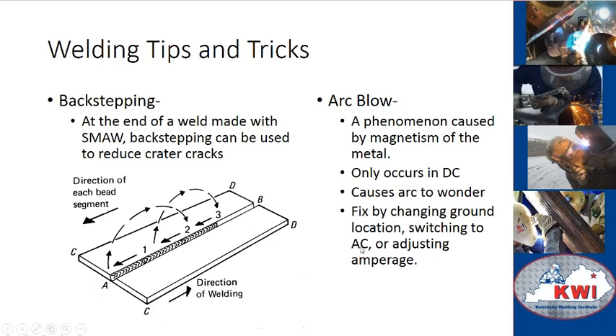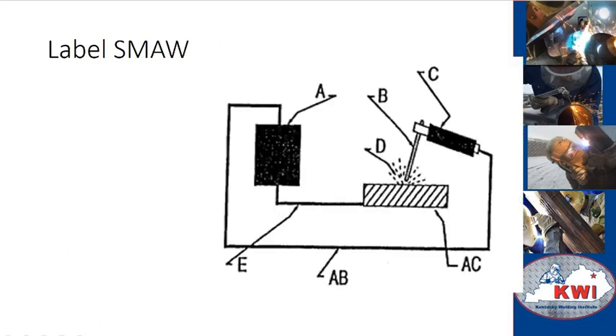You can switch to AC, which typically you can't do because you've got a DC machine or you're welding 6010s, or you can adjust your amperage up or down to try to pull some of that magnetism out of it, or you can change the ground location. So if you're welding towards your ground, then move it away. If you're welding away from your ground, then move it towards. But play with the ground and try to pull that magnetism out of that.